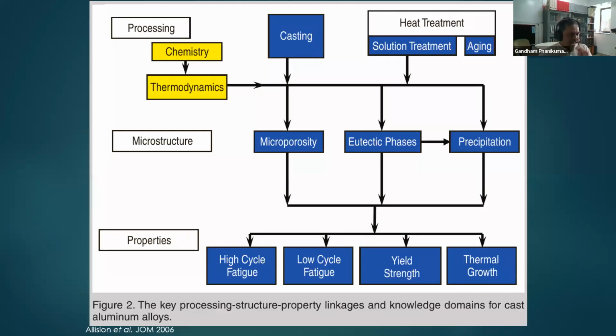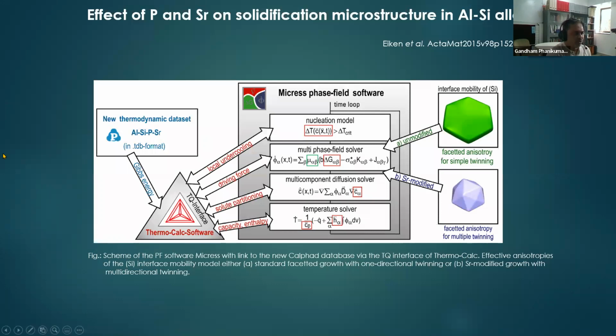So today, as you look at the various stages of alloy development, like casting or printing or porosity, eutectic phases, precipitation, all kinds of things are now possible to be captured by simulation. And the software we are talking about, Micress, talks to Thermo-Calc and takes into account the actual alloy information and gives you parameters such as the driving force, chemical potential, Gibbs energy differences, compositions, and so on, or properties like heat capacity. And therefore, it will be able to simulate the microstructure. Okay, so that is a capability today.